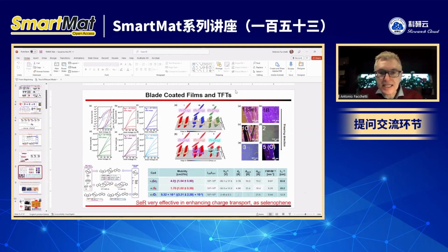So these are examples of intramolecular lock. For oxygen there is very low mobility, and this is typical for this type of molecules. Oxygen has never been very, very good as a furan or as an alkoxy. It's not really been very good typically. But if you see selenium and sulfur, their mobility is very, very high. Those are very stable mobilities.